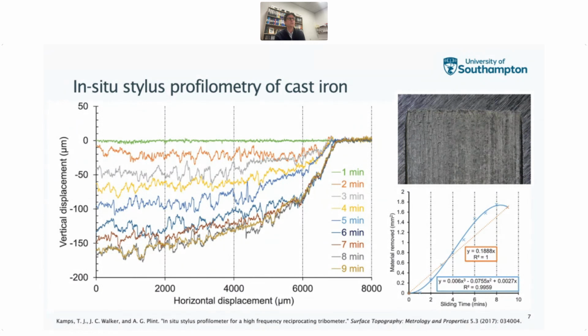But what really caught our eye was why this green line up here was showing almost no wear initially, and we're having quite a low friction coefficient of 0.3, and we speculated that perhaps this might be an oxide film that was protecting the surface for a little while before being disrupted and damage accumulation occurs.